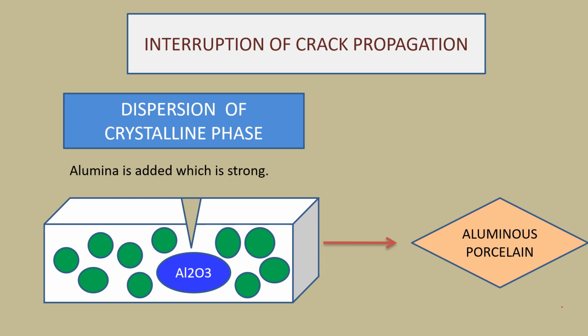Then moving on to the next method, that is interruption of crack propagation, and this can be discussed under two headings, that is the dispersion of crystalline phase and transformation toughening. In dispersion of crystalline phase, you are going to add a crystalline material which is considerably strong that doesn't allow the crack to propagate through it, and here alumina, which is a crystalline material, is added to the porcelain, and this alumina is a tough material and doesn't allow the crack to pass through it. This addition of alumina to the feldspathic porcelain resulted in the development of aluminous porcelain, in which the deeper layer will be aluminous porcelain and the top layer will be feldspathic porcelain.